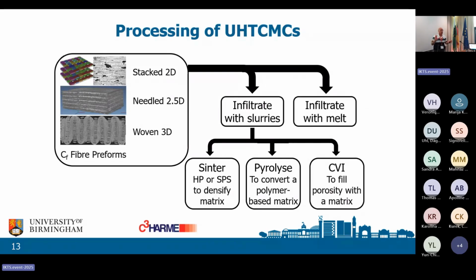Essentially, though, you start with the fibers. When you're making any composite, you start with the fibers. You can have stacked 2D fibers. Just stack the layers one on top of another. Works well, it's cheap, it's effective. The problem is they have a habit of delaminating. And if you're flying at Mach 5, you really don't want your leading edge to delaminate.